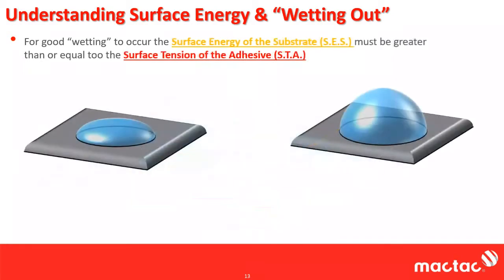So I'm going to take it a step further here. Now we're looking at two different surfaces, and the first thing you notice is that the bead of adhesive looks different between the two. Just for this example, keep in mind that the same amount of liquid, say fictionally 3 milliliters of adhesive, was applied to both surfaces. And what you notice is you get a much different looking bead.